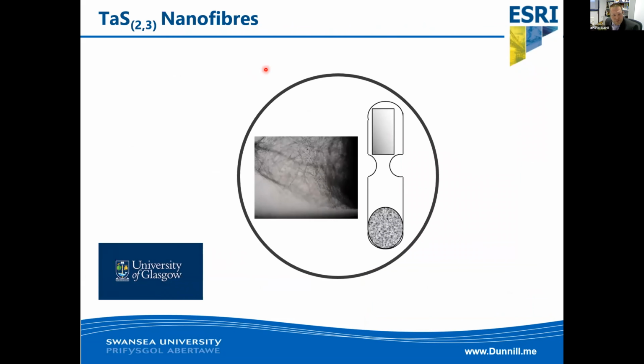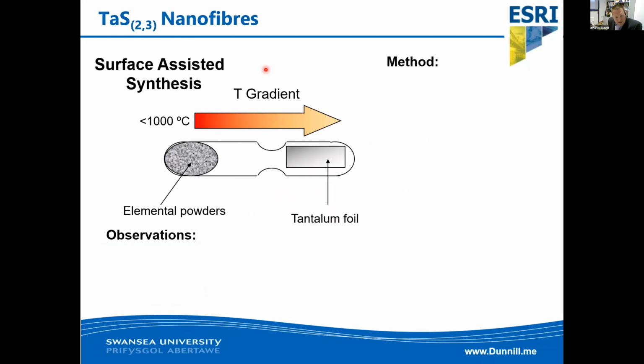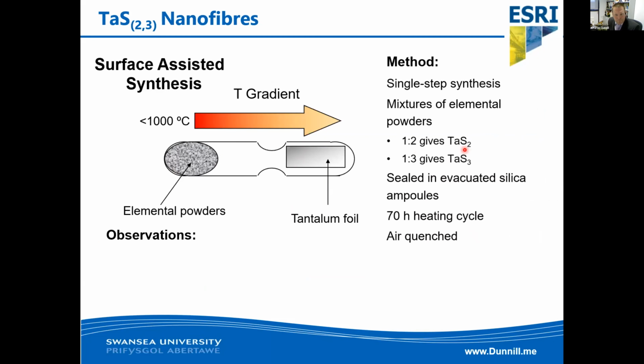Okay, so moving on to the second system, which was more about my PhD work at University of Glasgow. We were interested in chalcogenide structures and looking at the different syntheses of these. So we've got a quartz ampule synthesis here, where we actually use glass blowing techniques to seal quartz ampules. We can put elemental powders in one end. We can do a surface assisted synthesis with some tantalum foil in the other end, and this little neck that we've blown into the glass prevents the two from actually mixing.